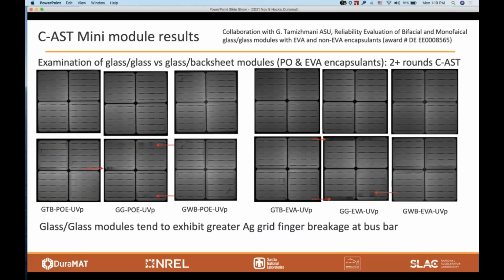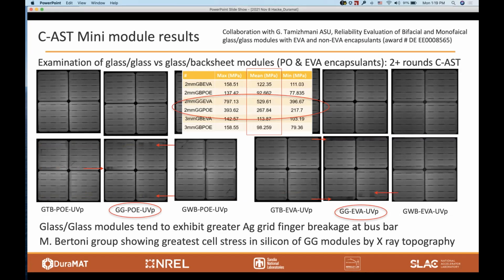And already what we can see is in the glass modules, fairly significant grid finger line breaks. So this has got some commonalities with another DuraMAT project out of ASU. Marianne Bertoni's group is showing the greatest cell stress in silicon in glass modules, whether it be a polyolefin or EVA. Although maybe the EVA in this case is showing somewhat higher stress. So this is in the cell using the X-ray topography. So it is possible that the commonalities we see, that's to say higher stress in the wafer, are associated with the grid finger breaks.